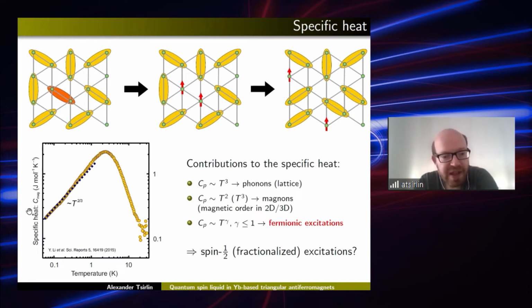And in this case, indeed the power law was quite unexpected. We got an exponent of about 2/3, so sublinear behavior. And that was the first indication that some fermionic-like excitations, some fractionalized spin excitations like shown here in the upper part of the slide, can take place in this material.